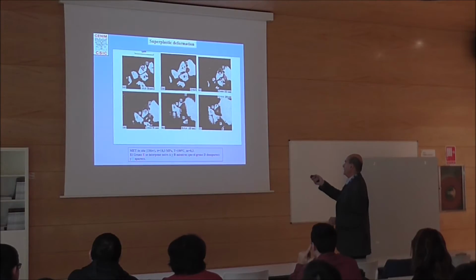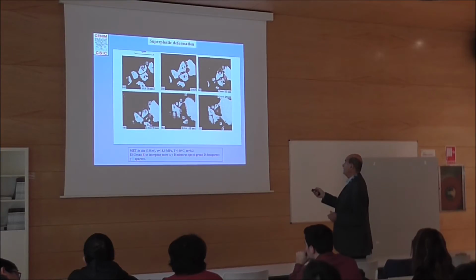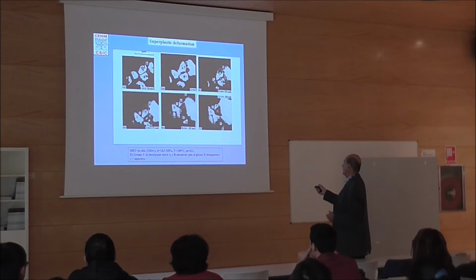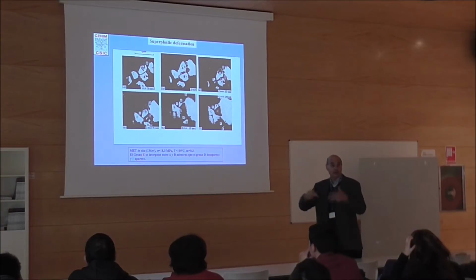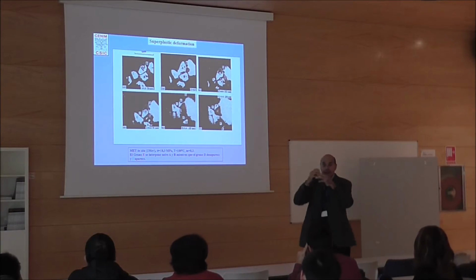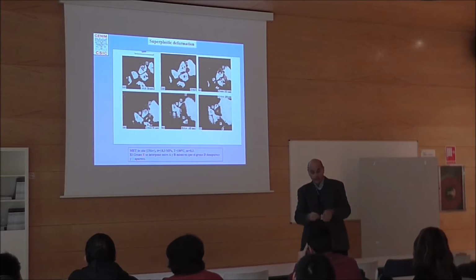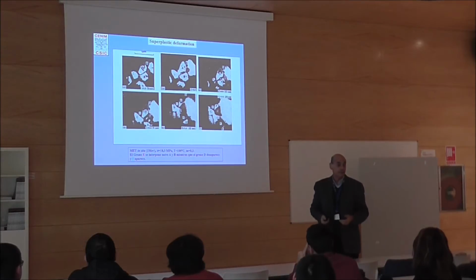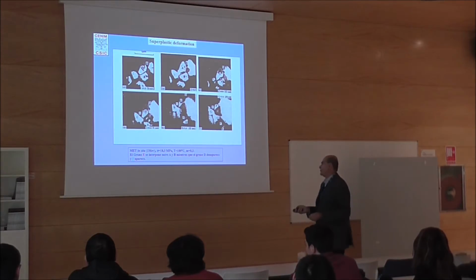And then this is very nice evidence in the microscope, in the TEM, where for instance you see a grain here, and with deformation, the grain changes neighbor grains, and disappears while another is created. So you have to imagine the grains in space, coming in, going out, and changing neighbors during deformation.